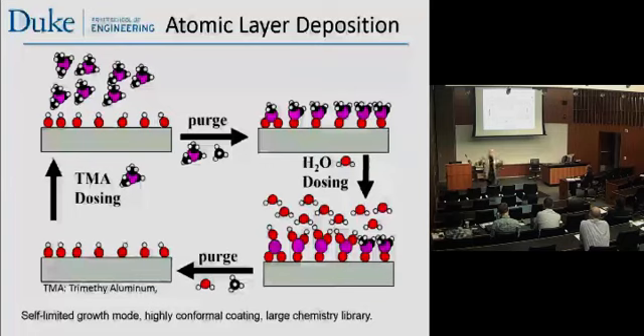So it deposits on that single layer, you pull a vacuum and get rid of all the extra material, you then treat the surface again with another nucleation layer or a transition layer, and then you do the whole process again. So you literally build it up atomic layer by atomic layer. I mean, that's exciting, right? That sounds fantastic. It's not nearly that good. It's not nearly as good as I just said. But that's the theory, and it's pretty close, depending on the material.